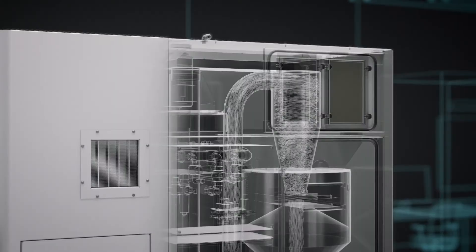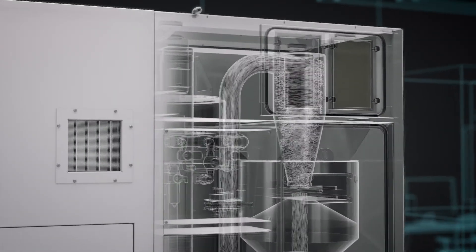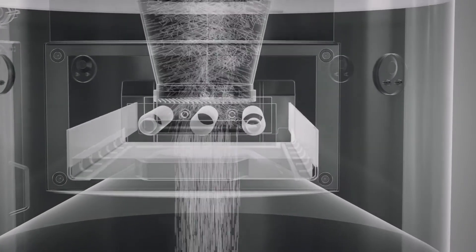In the PRS, smaller particles are removed in a cyclone cleaner. After that, the powder passes through a magnetic separator to remove any metallic satellites picked up in the cleaning process.